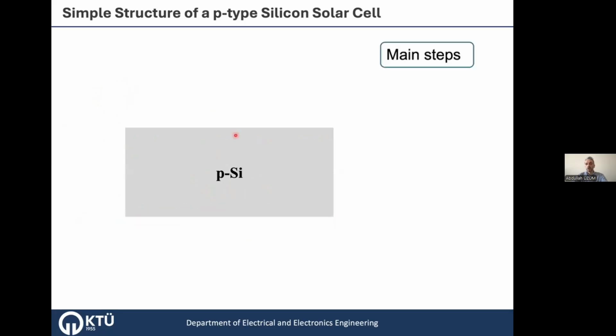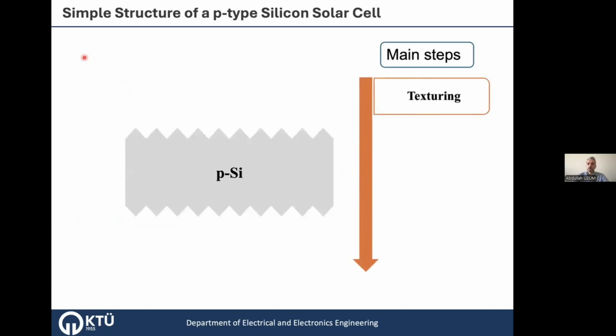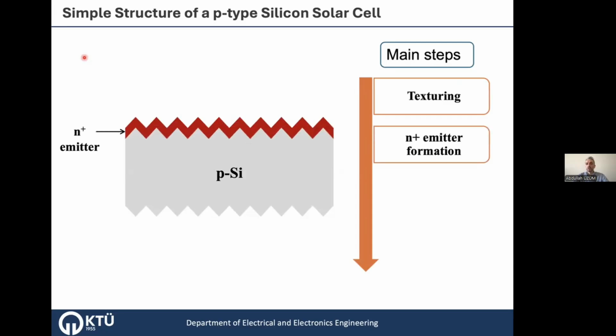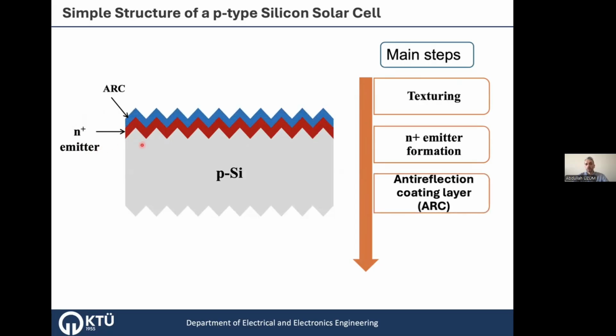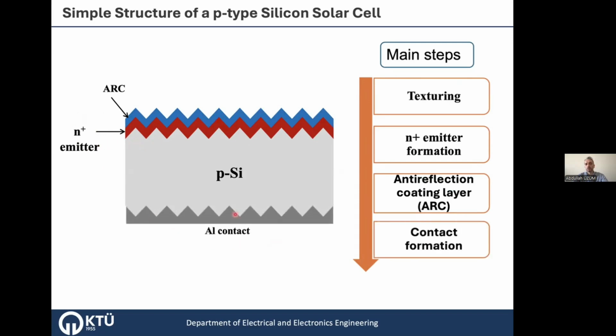So if we divide this into the 4 main steps, we will say that the manufacturing of the conventional typical silicon solar cells starts with the texturing process to reduce the reflection losses. We will be talking about that in a coming slide. And then the emitter formation to make the PN junction. When you form an emitter here, you have the PN junction, right? And then the anti-reflection coating on it to further reduce the reflection losses on the surface. And then aluminum back contact formation and front contact formation.